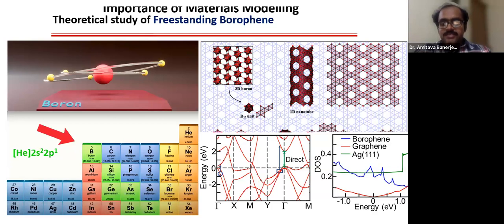Now to address this issue, researchers tried doping graphene with heteroatoms such as nitrogen, to increase the density of states at the Fermi level. But if you do this, the doping fails to be very effective, and it also causes immense damage to the crystalline structure, to its honeycomb-like lattice, in the long run. Here borophene comes into the picture, leveraging the metallicity of 2D boron sheets and the lightweight nature of boron. In fact, it has been noticed that some boron sheets could exhibit a specific capacitance on the order of 400 farad per gram, almost 4 times that of graphene. And most importantly, we can design the boron sheet only by changing the number and position of hexagonal holes, without adding any heteroatoms. That is one advantage, that we are not adding any heteroatoms.